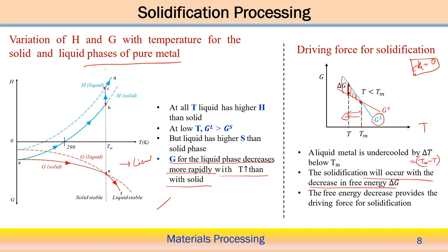But much more free energy is available, which makes it very prone to start the nucleation process when the degree of undercooling is much more, or the amount of delta G is also much more in this case. Now, the free energy decrease provides the driving force for the solidification. So, gradually the free energy decreases close to the melting point temperature, and that actually provides the driving force for the solidification to occur.